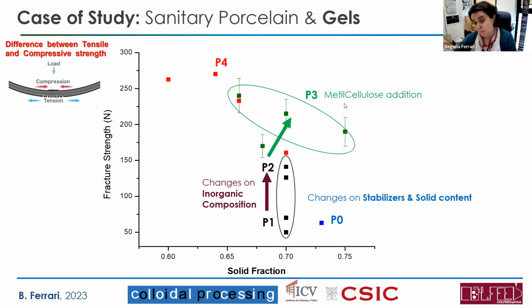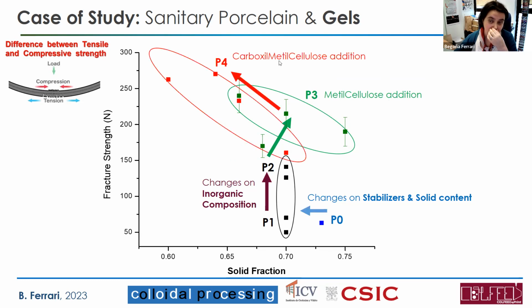But when we use methyl cellulose inside our suspension, and of course inside our green material, we can increase the fracture strength, even decreasing the solid fraction. And if we use a better modifier, if we use carboxymethyl cellulose as a structure in our suspension, we can achieve an even higher fracture strength with a very, very low amount of solid fraction. So definitely using a stabilizer, choosing a better raw material, and also using different kinds of polymer structures can give us a better fracture strength, also saving the amount of material we use to prepare the suspension or the slurry, right?